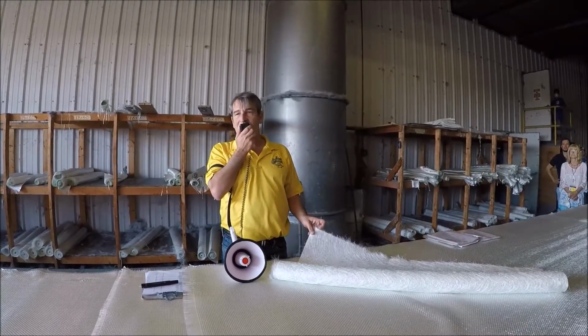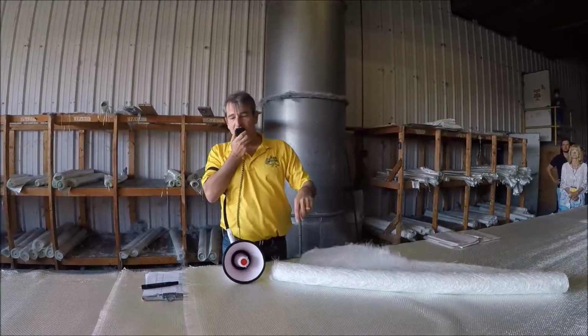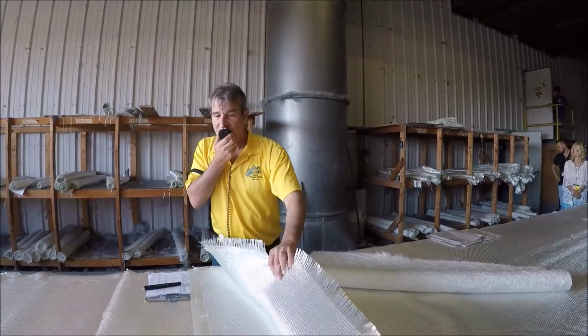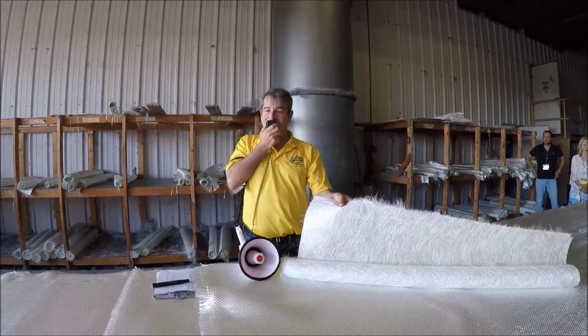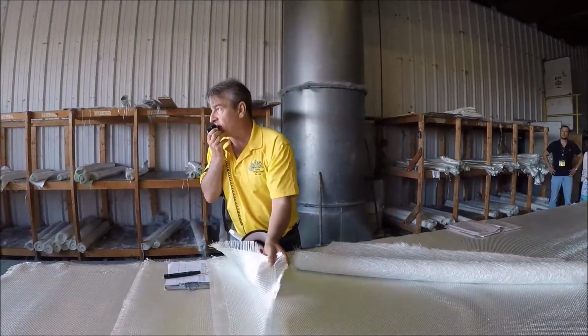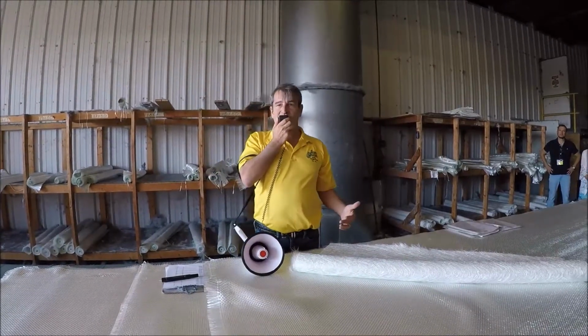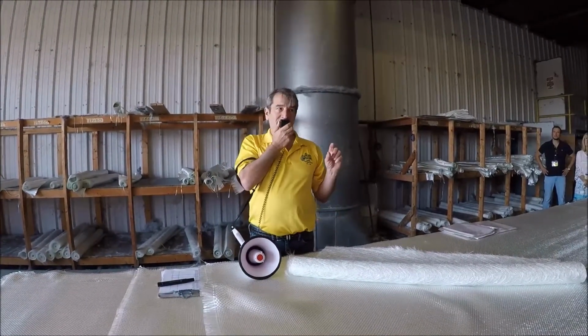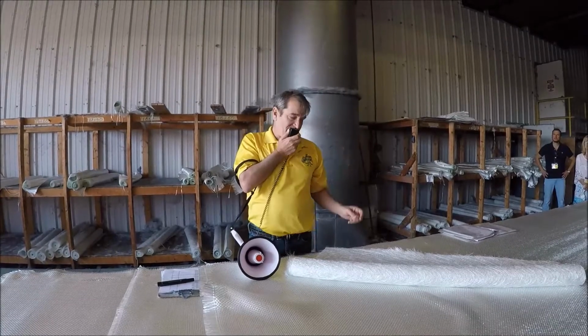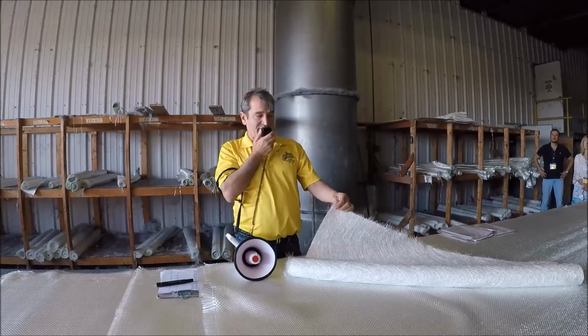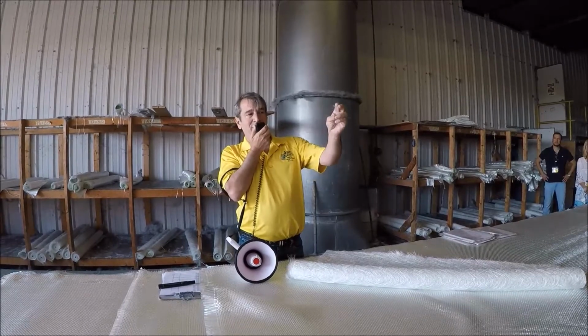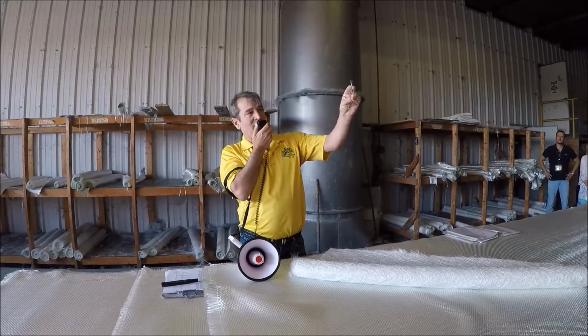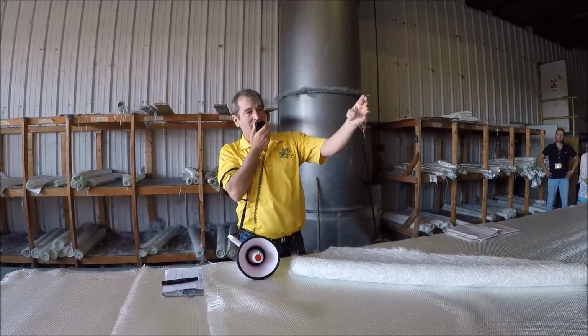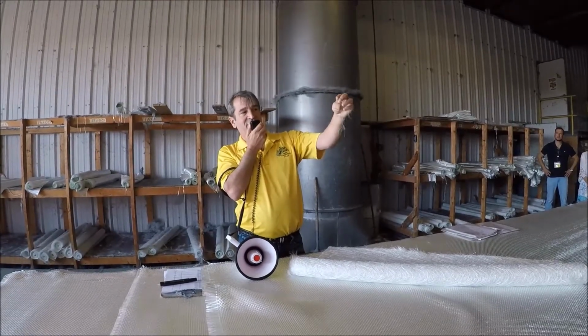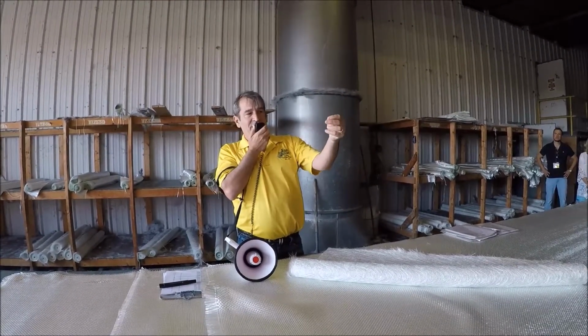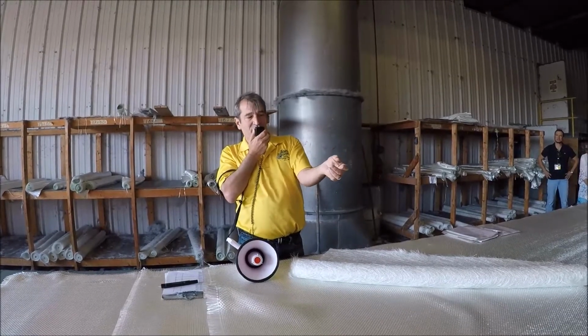Next thing we do is we come back and we put 1 layer of the mat, 1 layer of the woven roving, 1 layer of the mat, and 1 layer of the woven roving. And those 5 layers represent the physical laminate of the pool shell. If you look at the material, this mat material, you can kind of pull it apart, and it's only about 1 inch, 1.5 inches long. And you can pull it apart until you get a single fiber, and that fiber structurally is only bridging a small area.